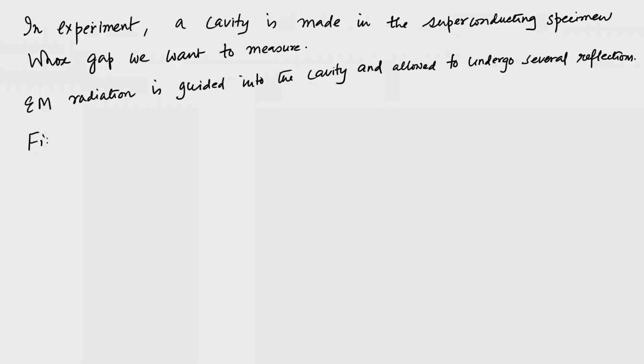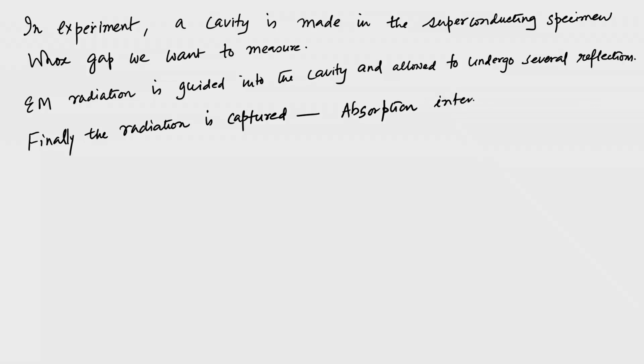Finally, the radiation is captured after it has undergone multiple reflection and hence absorption. So, what we actually see is the absorption intensity of this radiation. And what happens is that this absorption intensity of the radiation is actually plotted as a function of the frequency.